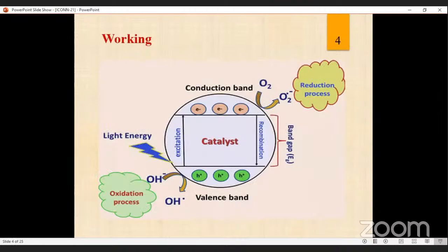We know that the most widely used photocatalysts are semiconductors, that is TiO2, titanium dioxide, and zinc oxide. But they have their own limitations: after the water treatment, they need to be pulled out of the water treatment barrel, which is very difficult. And they also have a limitation with the amount of solar energy utilized for photocatalysis. This is addressed by using magnetic particles, that is ferrite, which help in tuning the band gap of these semiconductors down to the visible light spectrum.